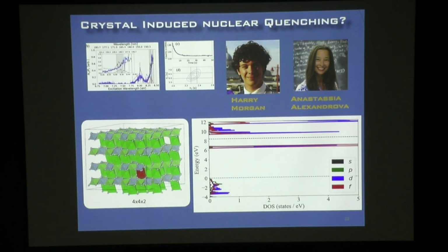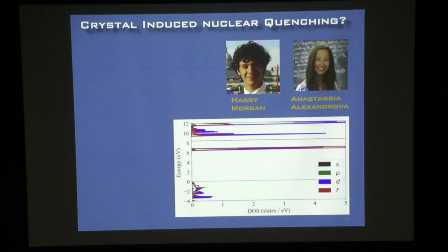So what we see here, this is the top of the valence band. Here's the conduction band. This is about a 10 eV band gap crystal. Right here are defect states associated with the thorium. You dope a thorium into the crystal, it has to change a little bit to accommodate it. Some extra fluorines come in. And so these are excitations associated with the thorium, and they have mostly F character and a little bit of D. Now, here is the nuclear energy if I just draw it on here. This is where we saw this region. It's about right here.